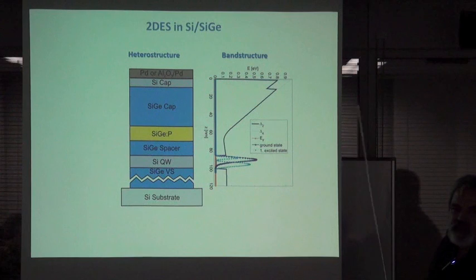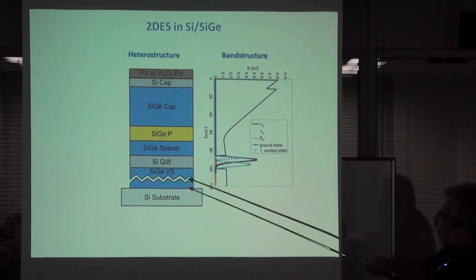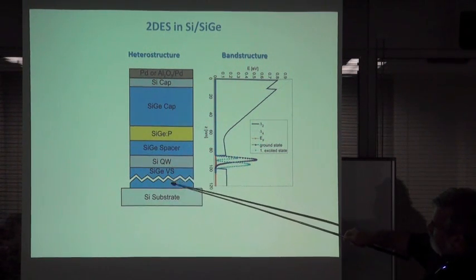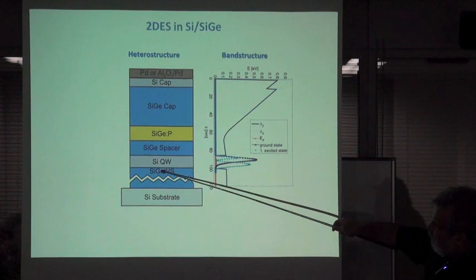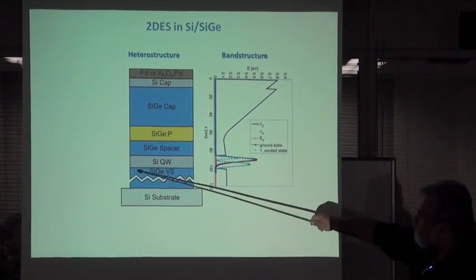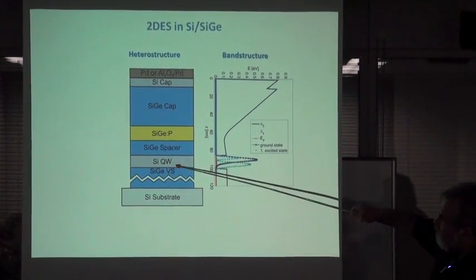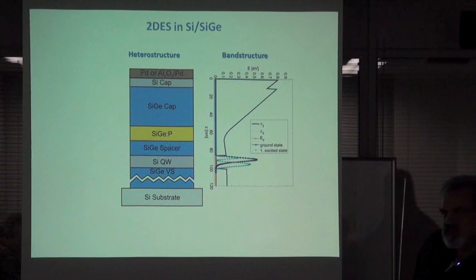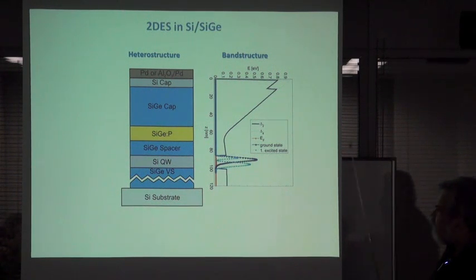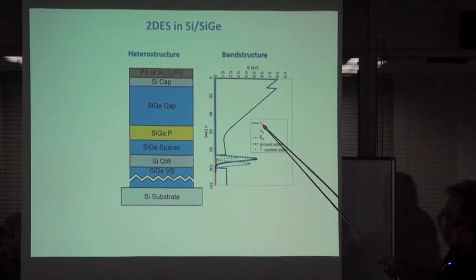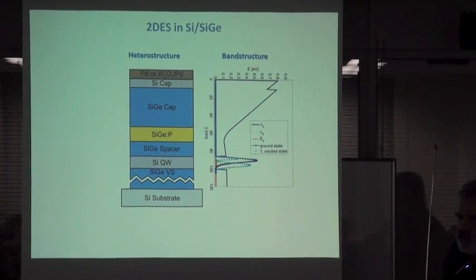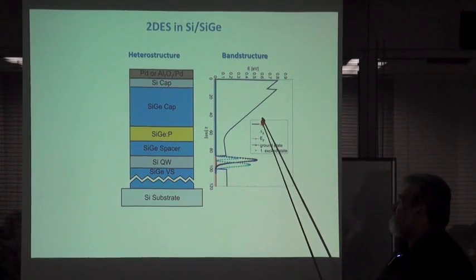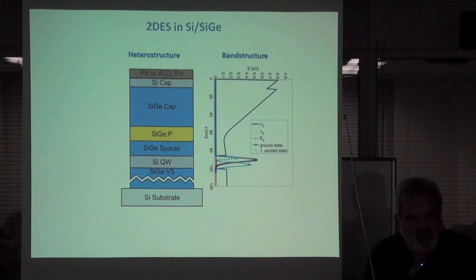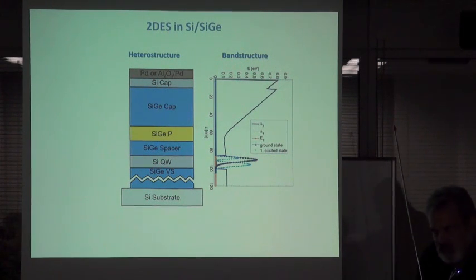Germanium has a 4% larger lattice constant. So if you relax the lattice constant here by adding germanium to silicon, you have a so-called virtual substrate, and then you strain silicon, and actually you then have tensile strain in silicon, which splits the conduction band, and you have the lowest conduction band minimum, delta 2. This was first done in my group together with Daimler in 1984.